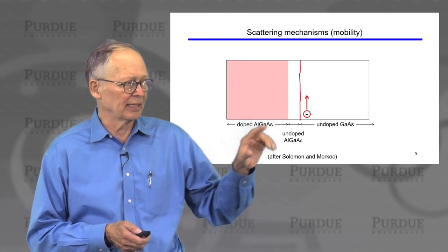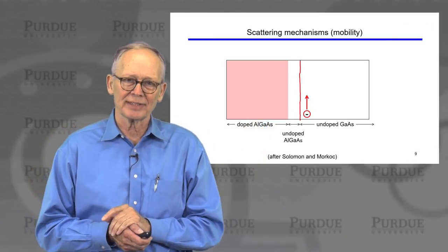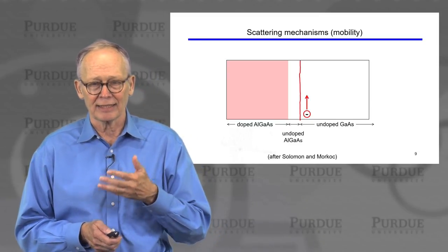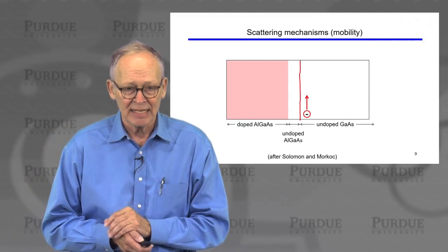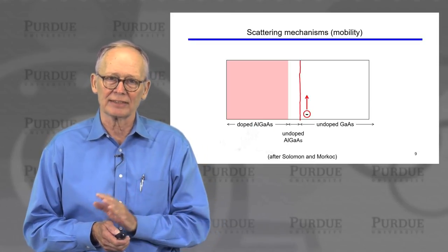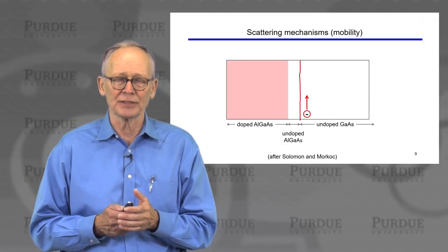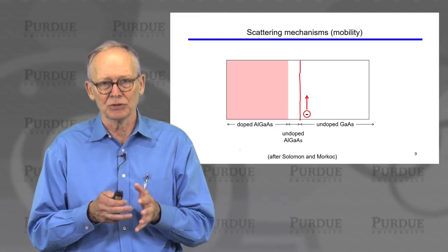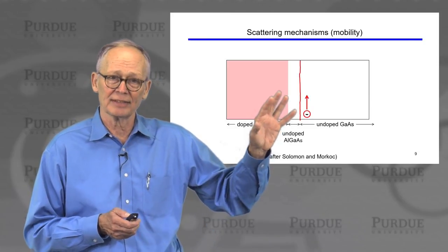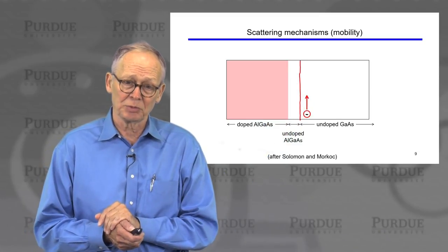The layers are grown using sophisticated epitaxial techniques: molecular beam epitaxy (MBE) or metal organic chemical vapor deposition (MOCVD). These techniques can grow almost atomically flat interfaces between the small-bandgap and wide-bandgap layers — very different from the SiO₂-silicon interface, which has significant surface roughness that scatters electrons. The nearly perfect interfaces in HEMTs have very little roughness, which promotes high mobility.